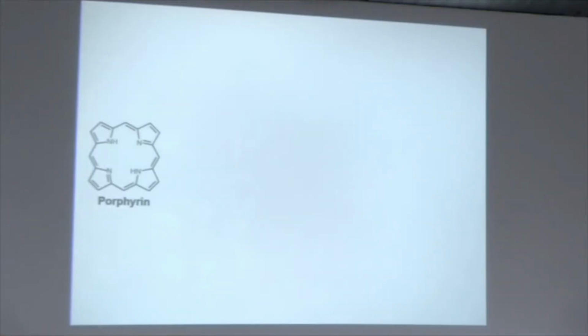It's fully aromatic. And if you look at the nitrogens, you have 2 types of nitrogens, one without a hydrogen and one with a hydrogen. And I will come back to that a little later. If you do XPS, these 2 are chemically inequivalent, and each of them gives a peak in XPS. So you see 2 peaks in XPS if you have this type of system. And this will be very important for the talk. And these molecules are really, really important in nature. They make up all the colors, or many of the colors, together with phthalocyanines in nature.